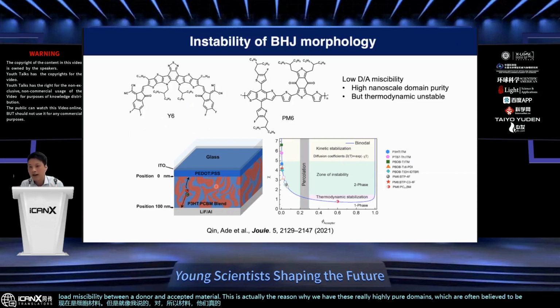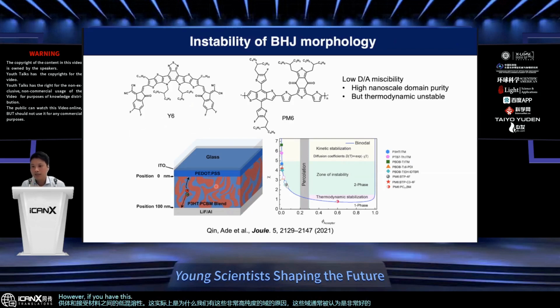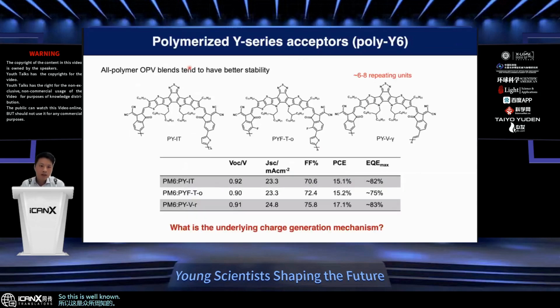which are often believed to be very good for efficiency. However, if you have this low miscibility, what happens is that, thermodynamically speaking, the two materials are actually not in a stable structural phase. Essentially, if you give it a bit of energy, which you will under sunlight, they will over time decompose, and you lose this morphology. So this is well known.